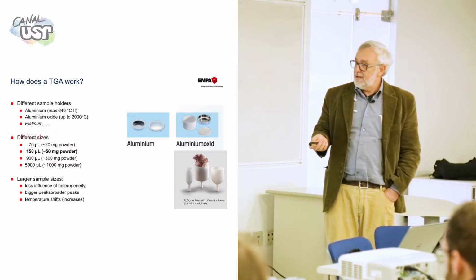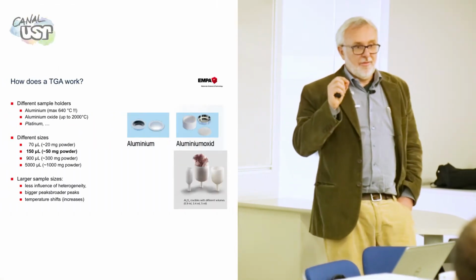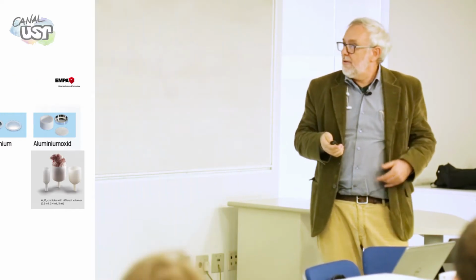We have different crucibles for different sample sizes. The largest that I know is this one from Netzsch. They can put 1 gram of cement inside of it. But the most common in the market, perhaps, is the 70 microliters, where you put 20 milligrams. There's a huge difference in terms of signal and the amount of weight loss. Since the scale is the same, you get more sensitivity in one than in the other, but it is going to influence the peaks, the temperature of the peaks. And of course, here you are much more sensitive to small amounts because you have more weight. But the peaks are much wider. You're going to see it.